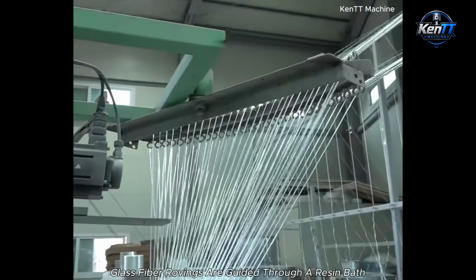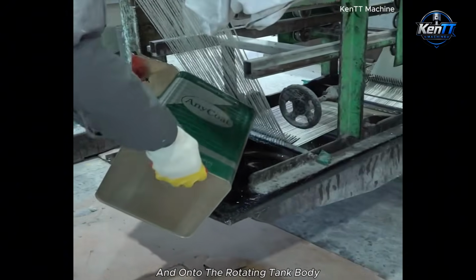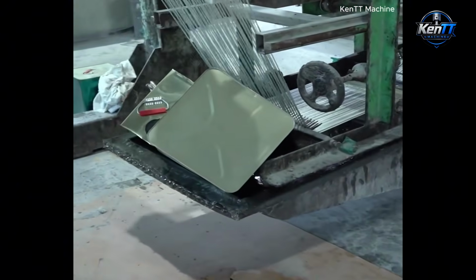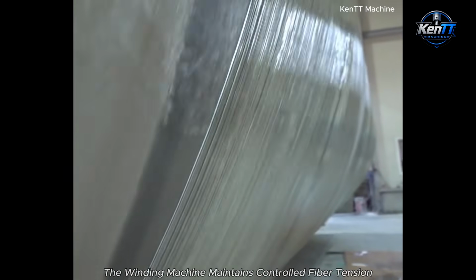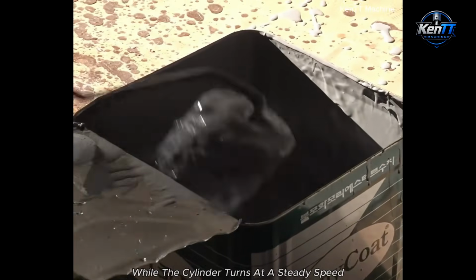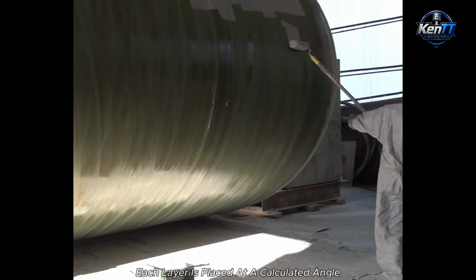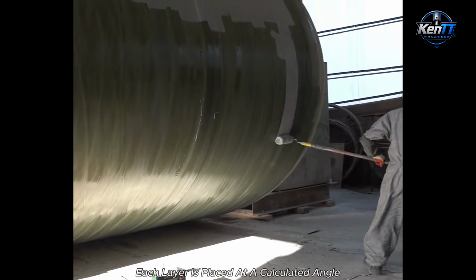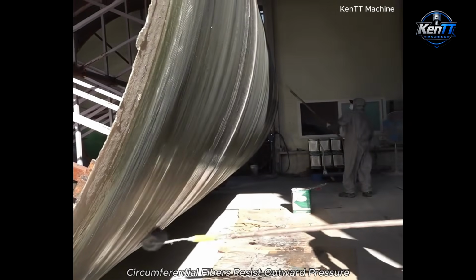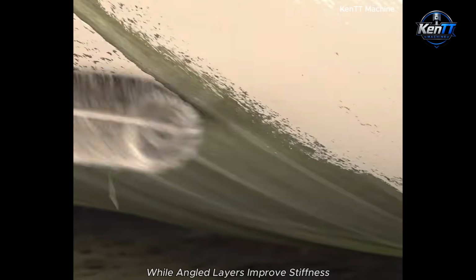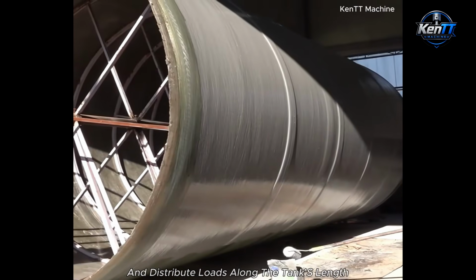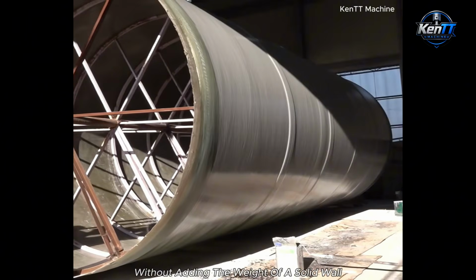Continuous glass fiber rovings are guided through a resin bath and onto the rotating tank body. The winding machine maintains controlled fiber tension while the cylinder turns at a steady speed. Each layer is placed at a calculated angle. Circumferential fibers resist outward pressure, while angled layers improve stiffness and distribute loads along the tank's length without adding the weight of a solid wall.